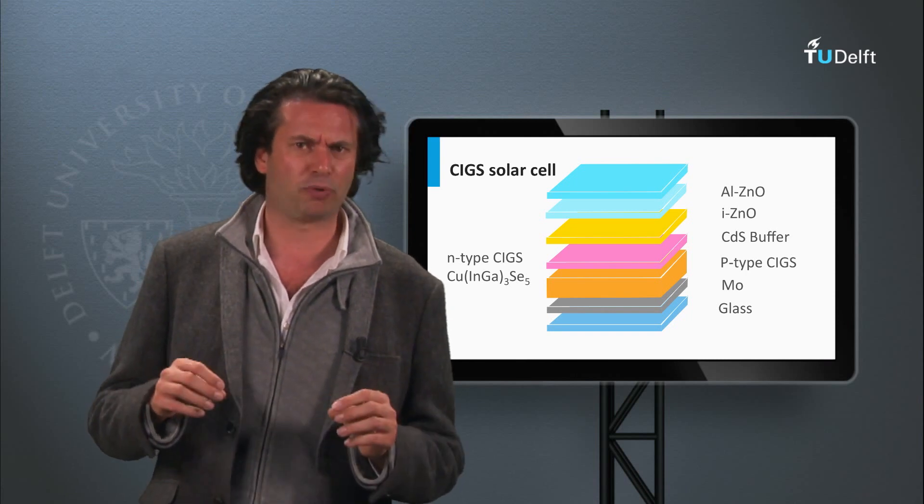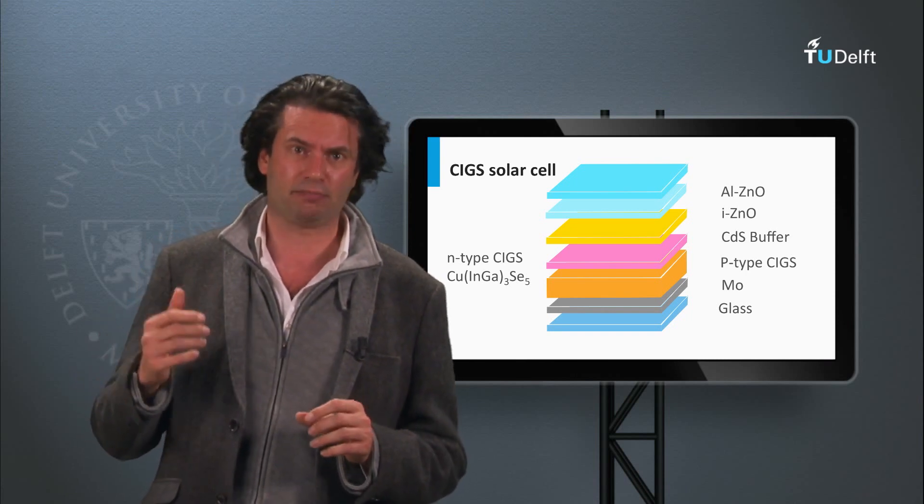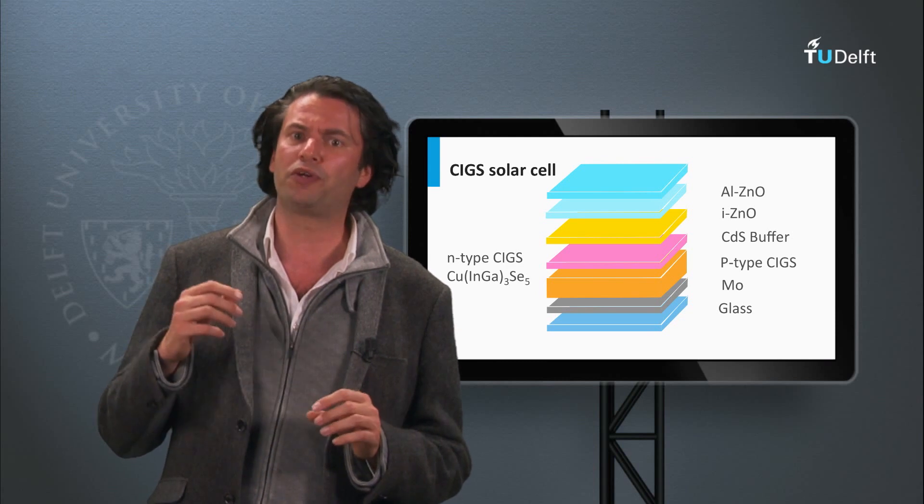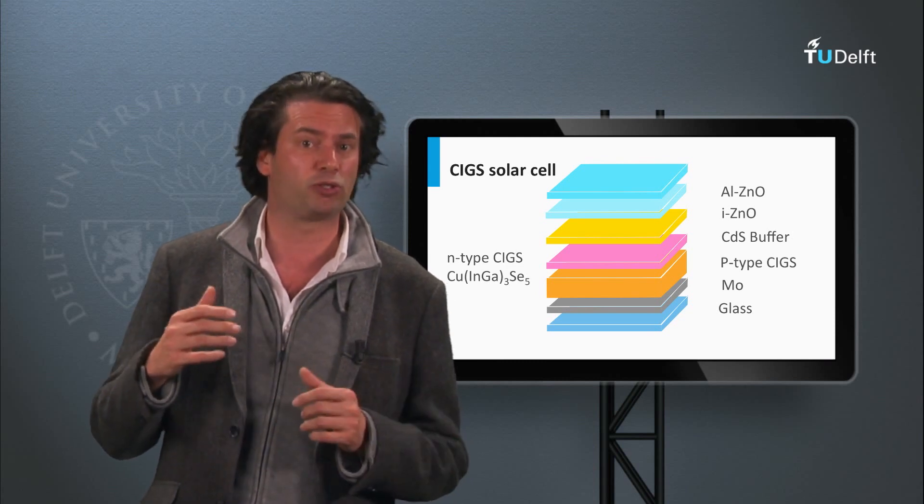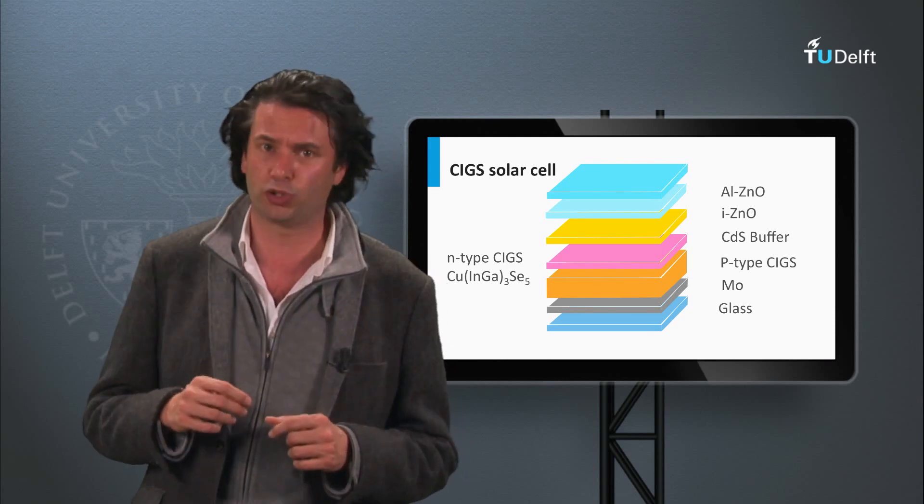In contrast, in copper-rich CIGS films, the Shockley-Read-Hall recombination at the CIGS cadmium sulfide interface becomes dominant.